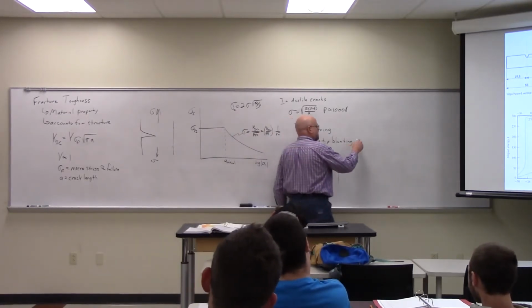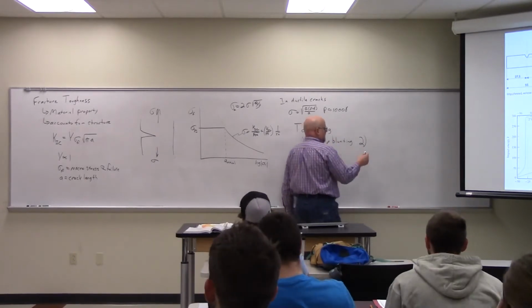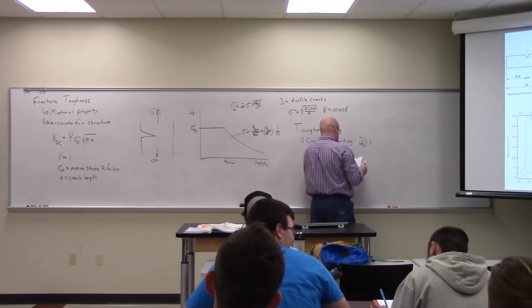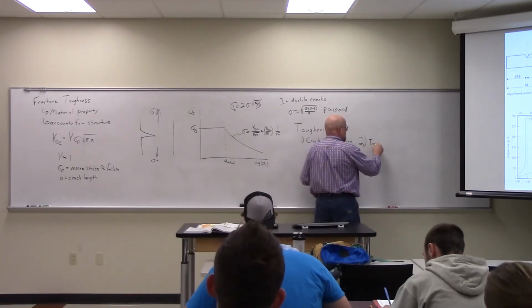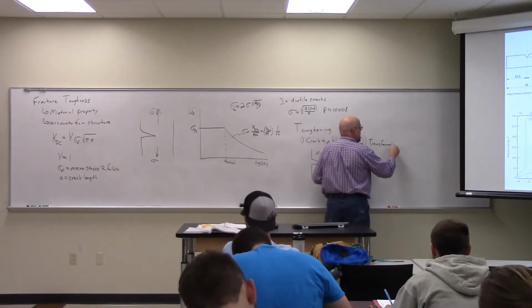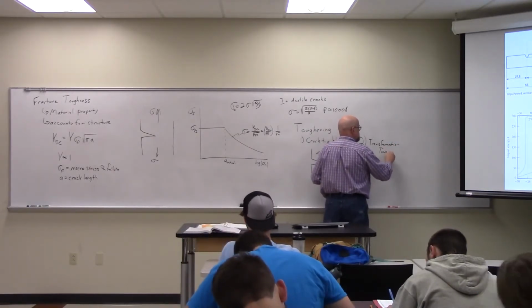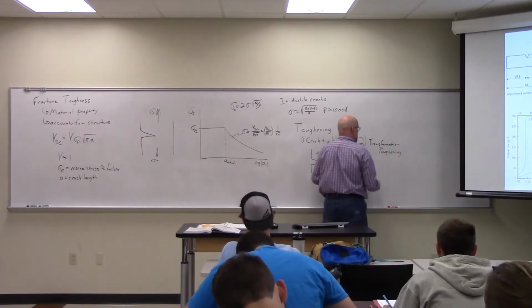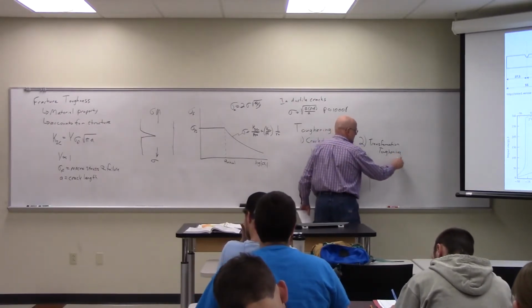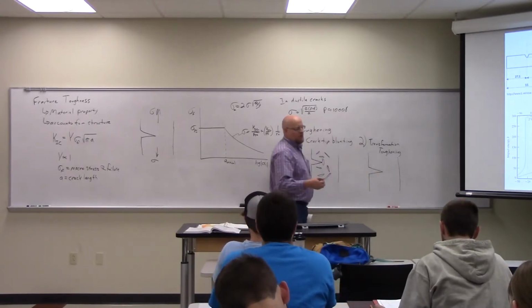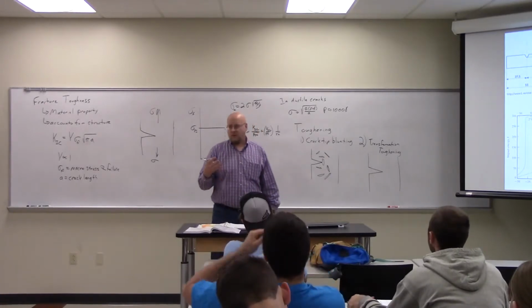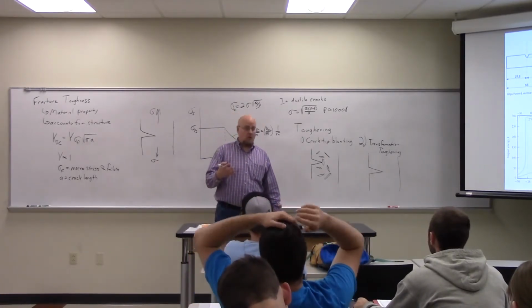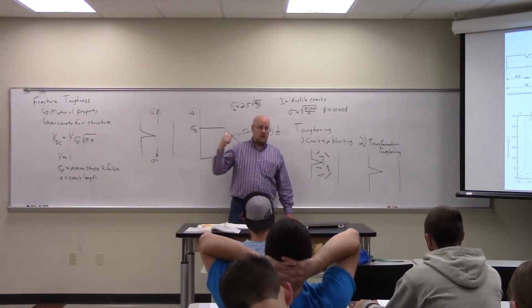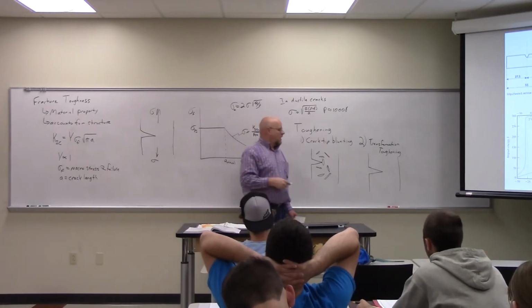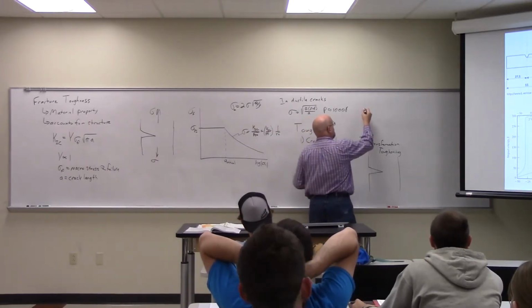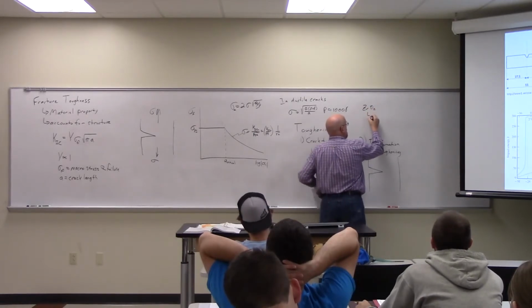And the second way that we can toughen is transformation toughening. Transformation toughening is where we take that same material and if you make it out of like zirconium oxide, that is the transformation toughened ceramic. So it's a ceramic material, and so it has high modulus and high strength, but it's brittle. And it's normally tetragonal.